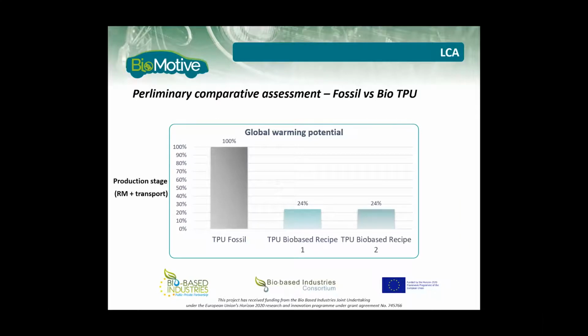The last topic is the LCA, the life cycle analysis. We also have a company within the consortium that's professionally dealing with such things. And what is a really nice result is that after they analyzed our bio-TPU recipes, they calculated that the raw materials transport for these TPU recipes has a decreased global warming potential, and this decreases by 76%. So that's actually quite impressive that the bio-TPU that we developed has such an impact.